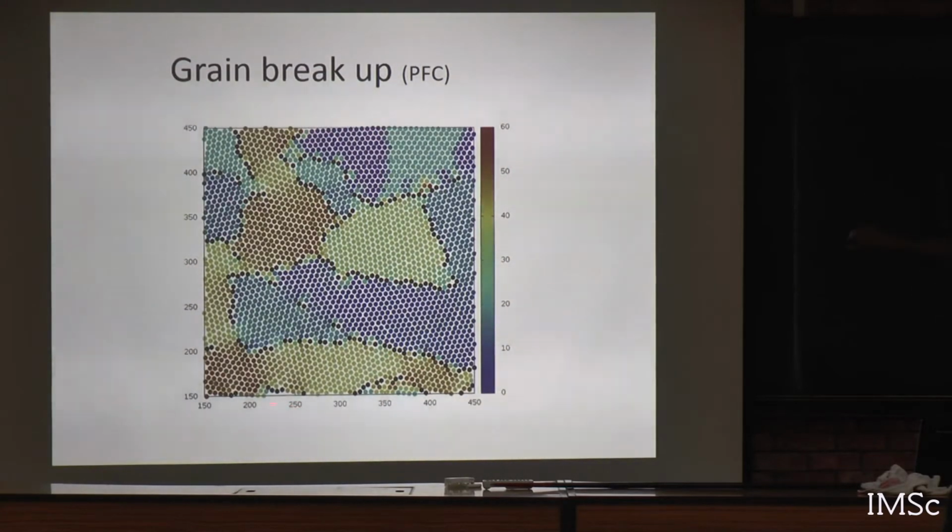You see defects, many of them together, moving in a very coordinated fashion, not necessarily near the wall. Near the wall you would expect that, because you are shearing, lots of defects come in. Sometimes you have avalanches, but this is not really near the walls. This is inside the bulk. So how does the breaking phenomenon happen? Just because these defects move in a coordinated fashion. Now if this was an equilibrium case, you would not see such coordinated movement of defects.